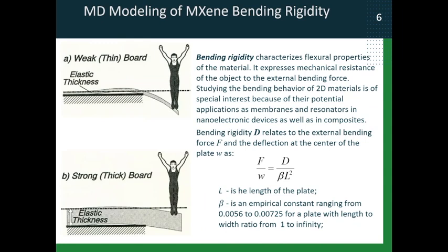Those were first measurements of Young's modulus on monolayer MXenes, and the values were surprisingly actually close to what we predicted using this simple molecular dynamics modeling. Next thing that we also worked on using modeling was bending rigidity of MXenes. And bending rigidity, the concept is intuitively very simple. So if you have a very thin material, right, then you expect it to deform very easily when you try to bend it. And when you have a thicker material, then it will take more force or more energy to bend it.